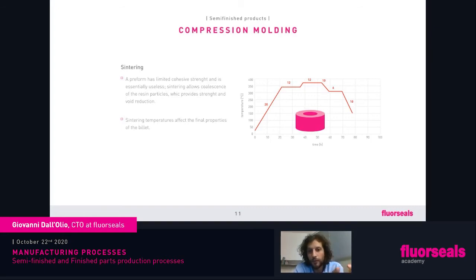Again, we will have another plateau to stabilize the temperature before the crystallization. So we are above the melting temperature, we melt all the crystalline. Now we have to create again this crystalline that gives strength and properties to our material. So it's really important that we control it. We have an even temperature in all the material, and we can start crystallization. All the material is at the same temperature, so we will have the same crystalline all over the material. That leads to very good mechanical and, generally speaking, PTFE properties. Also, 10 hours to cool down to a temperature that allows us to handle the material and go to the next production step.